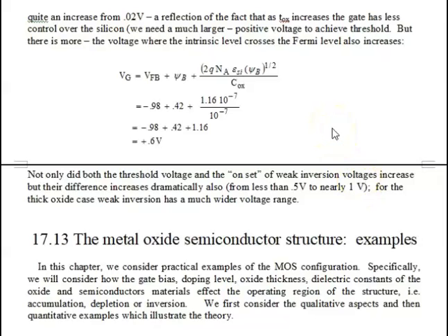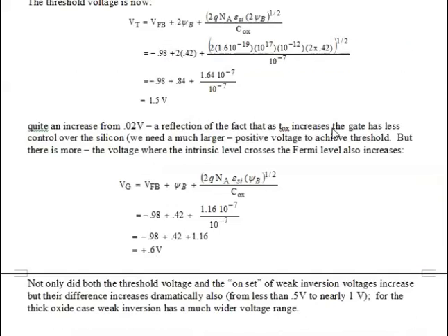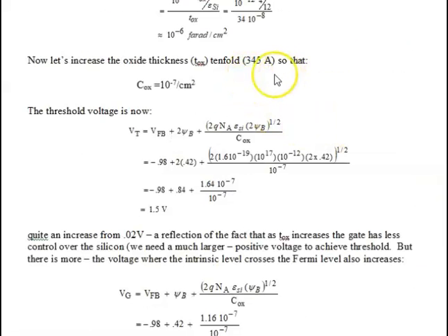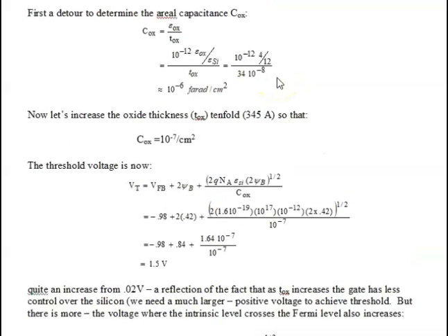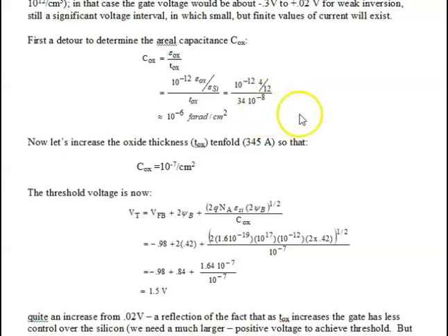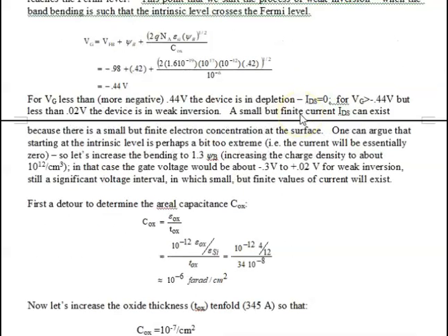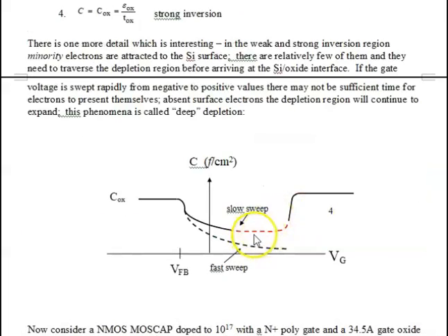So what we've done here is do exactly the wrong thing. We increased the gate oxide thickness, and I said, well, boy, we really need to make this smaller. And that is a good thing. We want to make it, in fact, much smaller than even 34.5 angstroms. And now we're well below 20 angstroms. The smaller it is, the more control the gate has over the silicon, and the smaller this region is between weak inversion and strong inversion.